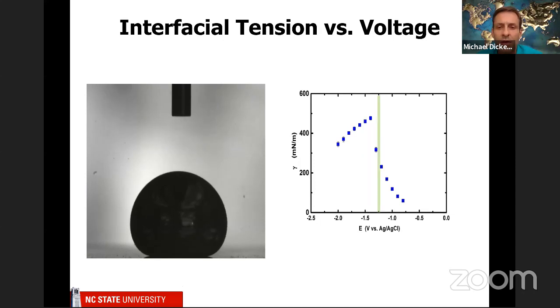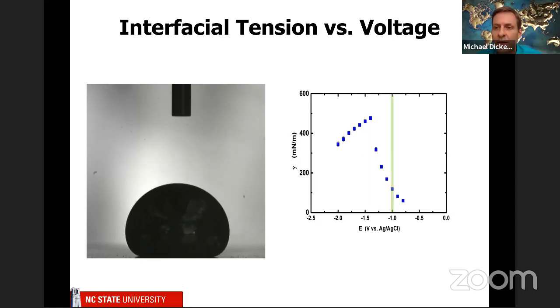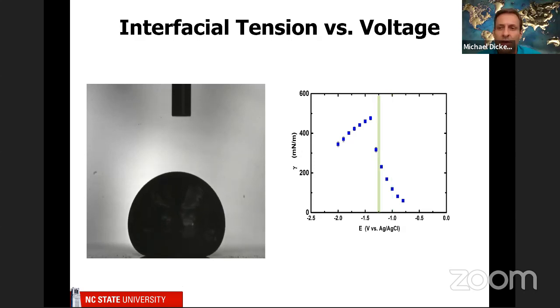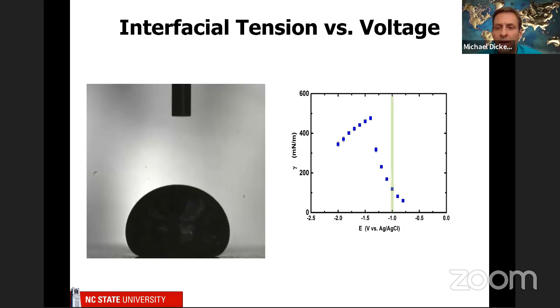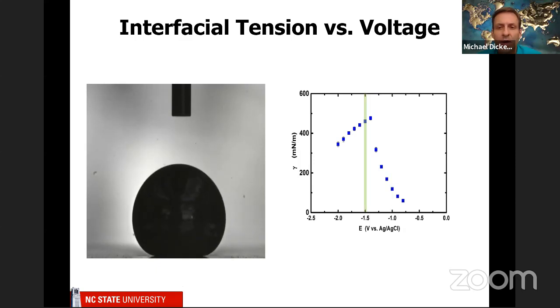And you'll see the droplet starts to squish, which means the surface tension is getting lower as it shows on the plot. And it's completely reversible. So we can go back and forth. This is all real time and has huge changes in interfacial tension. Now, what I was not able to tell you due to time constraints is that what the theory tells us is that the theoretical shape for surface tension versus voltage should be a parabola. And that's due to ions, basically charge at this interface that act like a capacitor. And then what actually happens is this does not follow the theory.